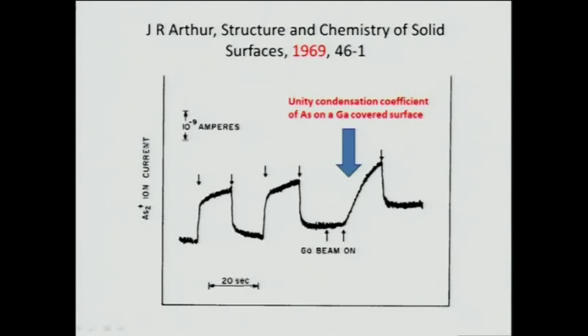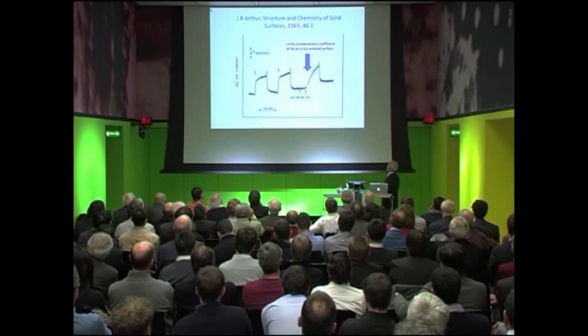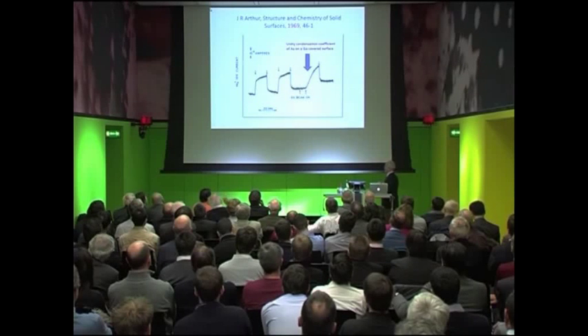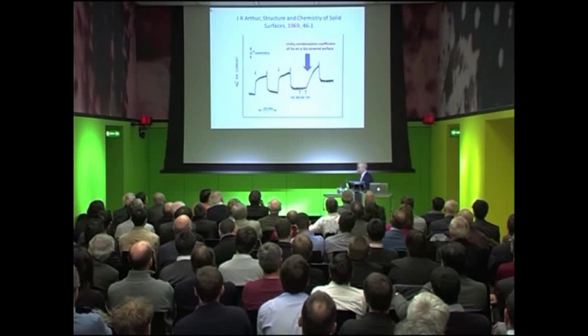But the important point is, when he turned on the gallium beam on the gallium arsenide surface, notice here, when he opened the mechanical shutter, instantly that exponential curve started. The magnitude of A equals 0. Therefore, arsenic has unity sticking coefficient on a gallium arsenide surface if the surface is covered with gallium.